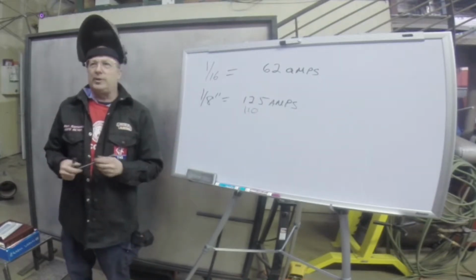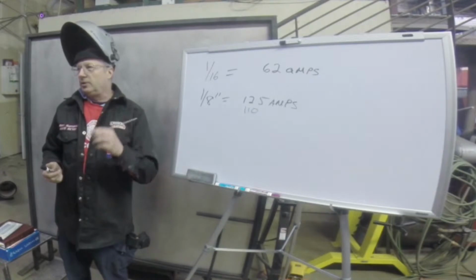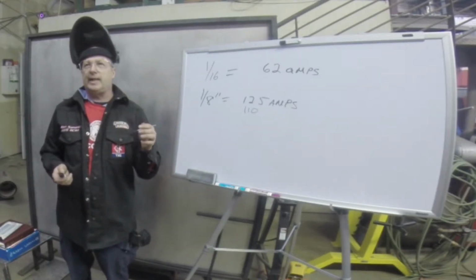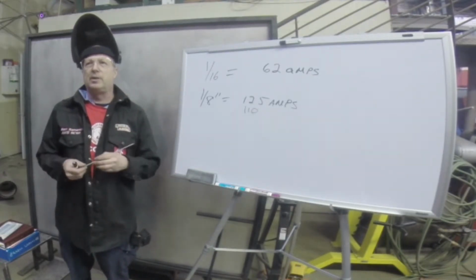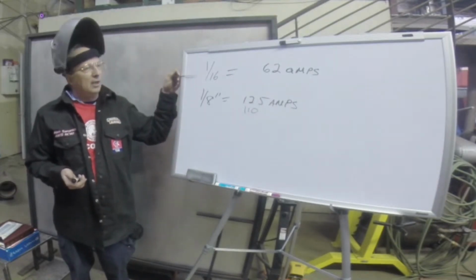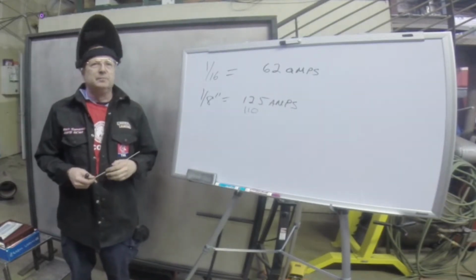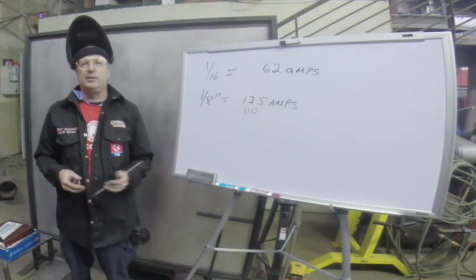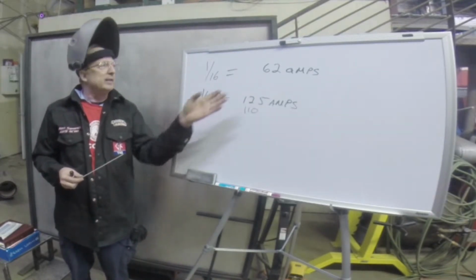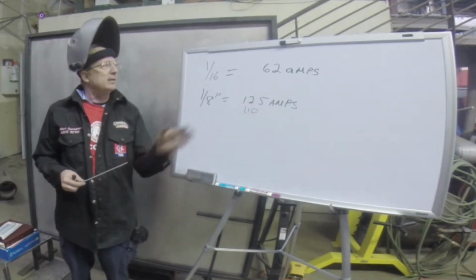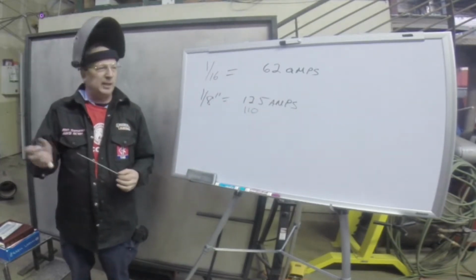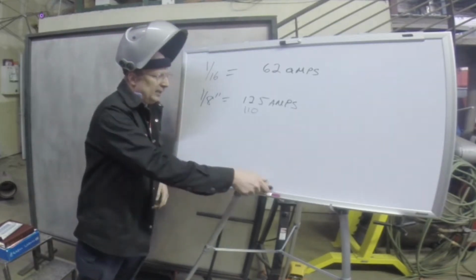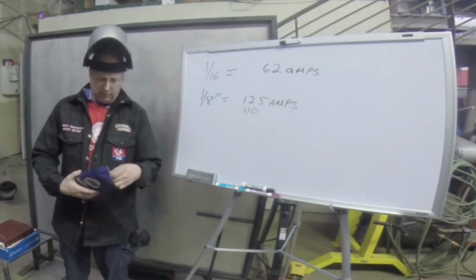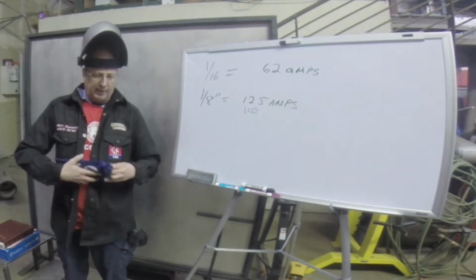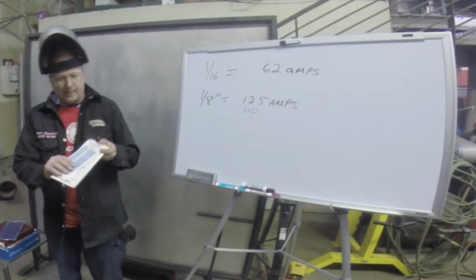The same will work with your TIG rod. Your tungsten electrode comes in different diameters, from 20 thousandths up to 5/32, your most common ones. So if you're using 16th inch tungsten like we're doing over here tonight, you're going to be around 62 amps is where you should be. Again, not exact, but really close. You don't have to spend hours playing with your machine. Now, say you forget what I taught you tonight, you can always go to a welding distributor or go to WeldComm.com. They sell what's called these welding calculators.